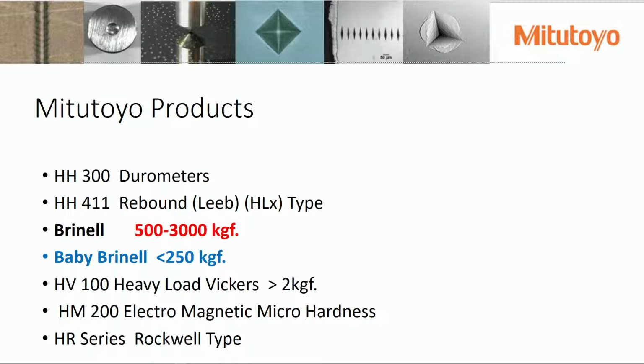So we have durometers, we have rebound testers. We do not have a full Brinell hardness tester, like the basic American version, which is 500 to 3,000 kilograms. We do have baby Brinell or light force Brinell up to 250 kilograms. Those generally use a 1 millimeter ball or 2.5 millimeter ball, a much more popular European specification. We have heavy load Vickers machines, generally 1 kilogram up to 50 kilograms. We have micro Vickers machines that are generally in the 10 gram to 1,000 gram range. And then we have our Rockwell type of testers.